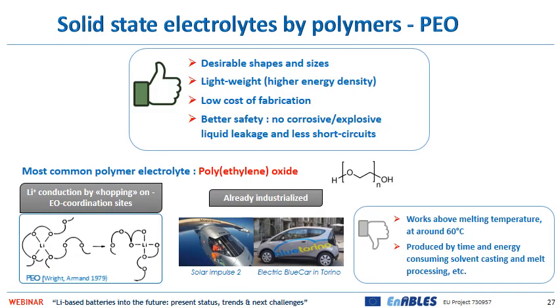Among all the different solid-state electrolytes, polymer electrolytes are very appealing for their characteristics, such as the simple preparation procedure and the possibility to be designed in several shapes, flexibility, and so on. The most popular polymer matrix is polyethylene oxide, PEO. During the 70s, Wright and co-workers demonstrated the capability of ether-based polymers to dissolve inorganic salts and exhibit ionic conductivity at room temperature. During the same years, Professor Armand posed PEO at the center of his research on polymer electrolytes.